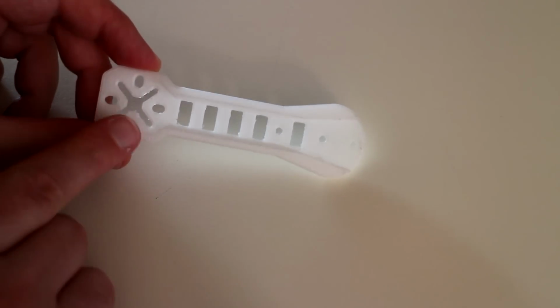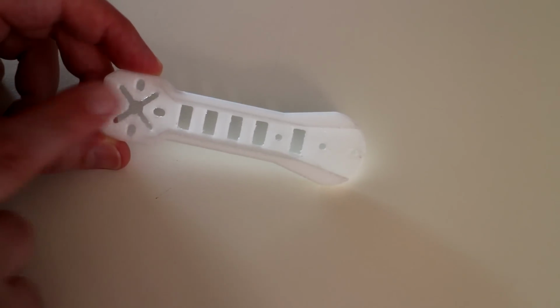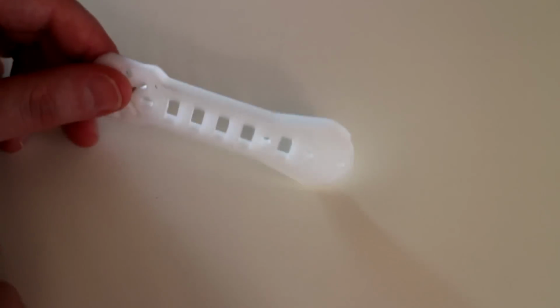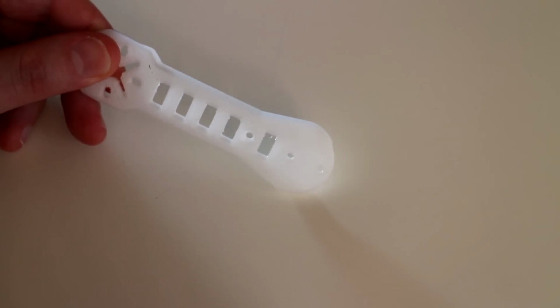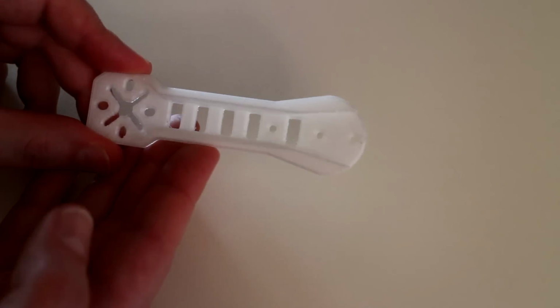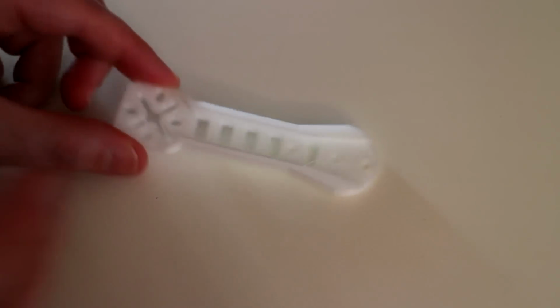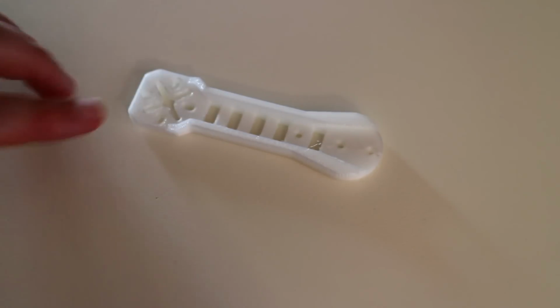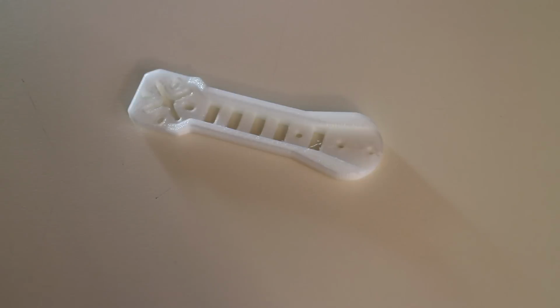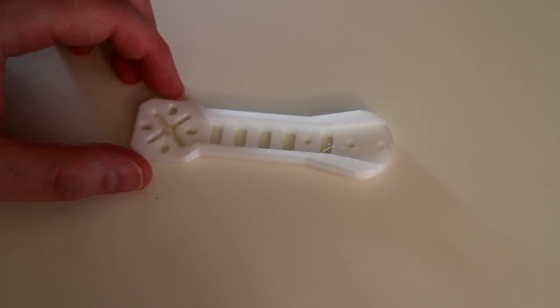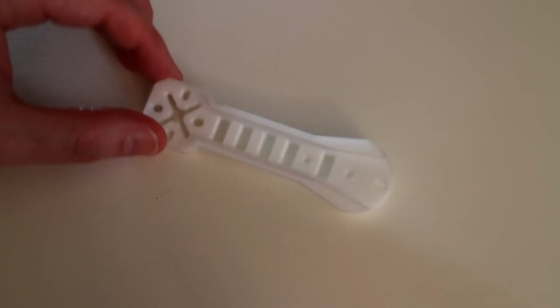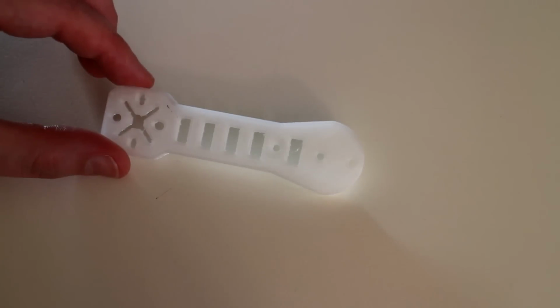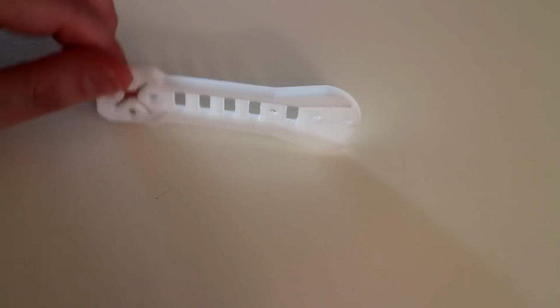The slicer settings for this part were three perimeters, three top and bottom layers with a 50% infill. The advantages of printing with this nylon bridge material is, first of all, it stuck down on blue painter's tape without an issue. It didn't bow at any point, and it was easy to remove once the bed had cooled down. Also, it's virtually odorless when printing this material.